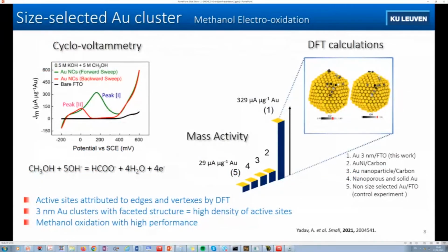So we tried to calculate the CO energy of adsorption on different sites. See, this is the corner, these are the edges, and we can see that there is a special site where the CO is adsorbed much more strongly here and here, and the same for OH. So from this investigation, we could see that this structure with these facets and edges are the very active sites. So if you have the same gold nanoparticle that doesn't have all this nice structure, it will not be very active.